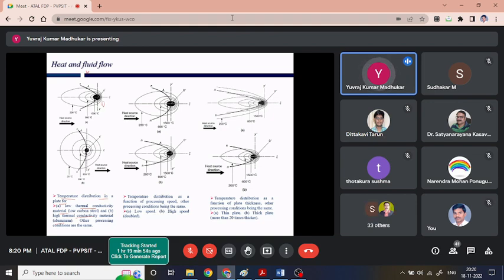So for a low thermal conductivity material like this low carbon steel, we can see the area on which the heat contour is being formed is very small, and behind the heating source the heat contour is forming for a longer distance. At the front it is going to be a very short distance. If you talk about a high thermal conductivity material, then the distribution of heat is relatively more in the front. However, it is happening over a larger area.